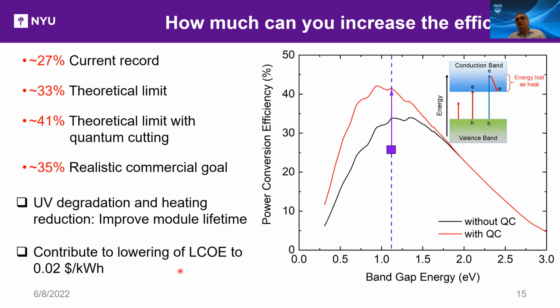So you might ask, how much can you increase the efficiency? Just to recap, the current record silicon lab efficiency is 27%. The theoretical limit, the Shockley-Queisser limit, is at 33%, which is right here. If you go back to the Shockley-Queisser paper and recalculate what is possible with a perfect quantum cutting material, one gets that the theoretical limit increases to 41%. So that's significant. This number is arguable, but something approaching 35% realistically is not out of the question.